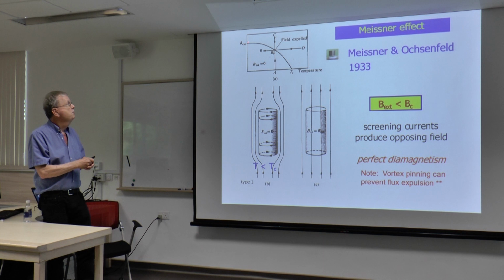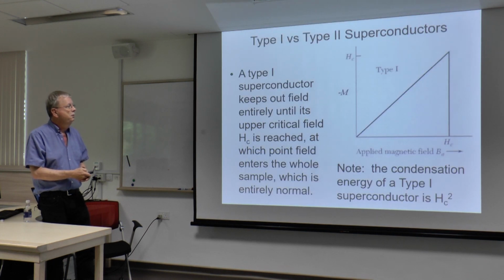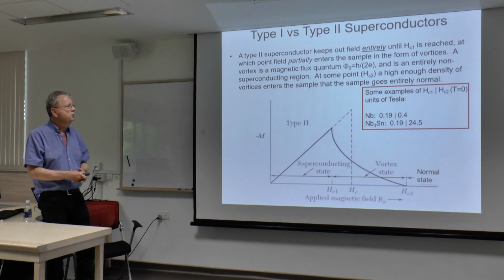I will always reference this one down here. It doesn't make any sense to reference anywhere along here unless you specify the temperature. So when you see a critical field, it's almost always the low temperature, T equals 0 extrapolation. So in niobium, which is one of, I think, approximately 3 type 2 superconducting elements, the lower critical field is